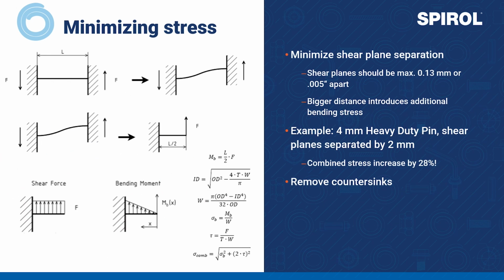Last but certainly not least, you should always minimize shear plane separation to achieve a clean shear load. The shear planes should be a maximum of 0.13 millimeters or 0.005 of an inch apart from each other, which is represented by clearance in the hub and shaft assembly, for example. And the more clearance and the bigger distance, that introduces an additional bending stress. To elaborate, if shear planes are separated by 2 millimeters, a 4 millimeter heavy duty coil pin would see an increase of combined stress of 28%.